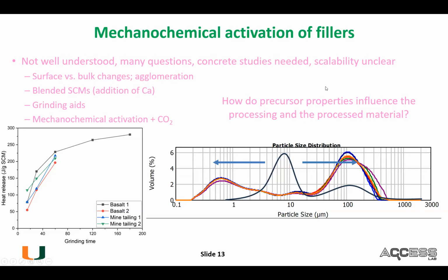As I mentioned to you, we're getting some sort of surface amorphization. So determining the depth of that amorphized layer is very interesting, and what controls that layer. As with every milling process, there is an agglomeration question, so limiting that agglomeration, perhaps by using grinding aids, is of interest. The other interesting thing is, during this process, can you bubble in CO2 or carbonate at the same time? That's also an interesting question.